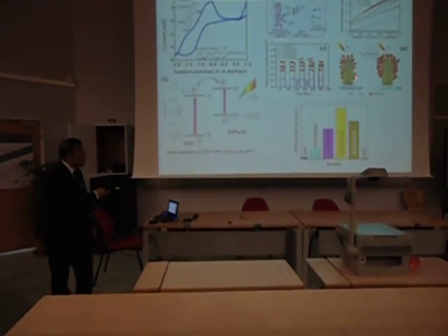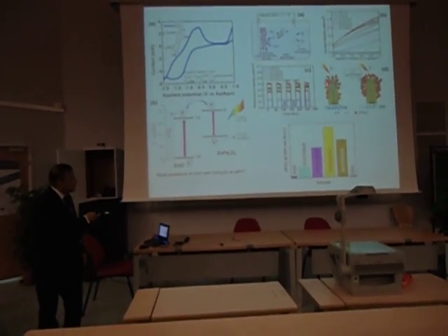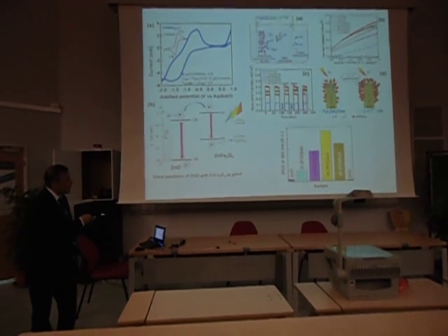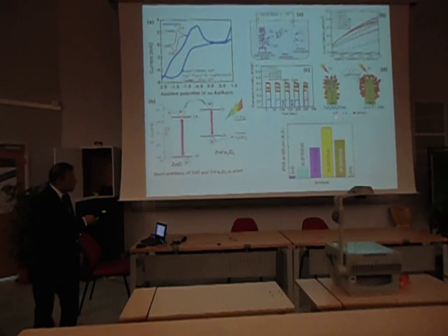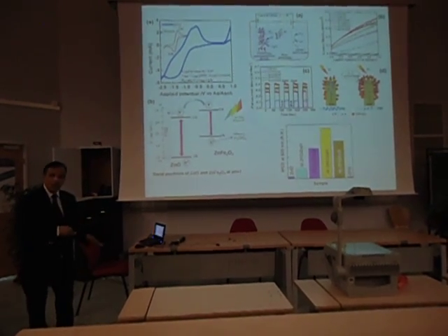So our structures are like this. We have zinc oxide nanorods here, which are actually dressed with ZnFe2O4 nanoparticles. So the optical absorption is actually taking place in zinc ferrite here, ZnFe2O4. On the other hand, the electron is transferred to the electrode very rapidly by zinc oxide.